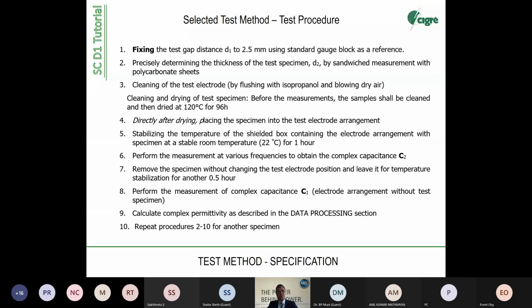So with the specification, we defined the fixing gap to 2.5 millimeter, using standard gauge blocks as reference, precisely determining the thickness of the samples, and cleaning, that's also important. If you ship the samples to Argentina or to Canada, they're in different conditions than when you submitted them from your production. So cleaning is very important, cleaning of samples and electrodes, taking care that electrodes are not corroded by means of specifying non-corrosive electrodes.